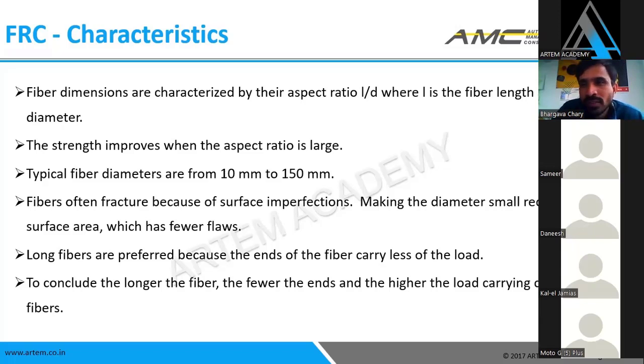There will also be some flaws, for example, due to surface imperfections, when we are not aligning the fibers in the right direction, there will be a fracture which occurs, and this fracture causes a failure. So making the fiber diameters smaller will reduce the surface flaws, because the surface will be very good when we use a smaller diameter and the L by D ratio is bigger.